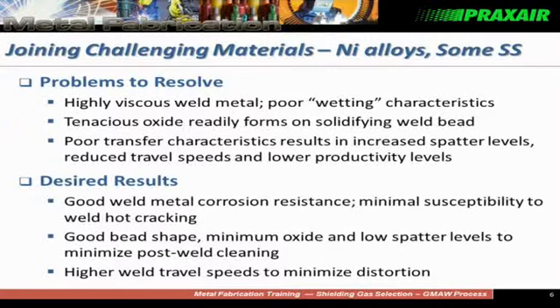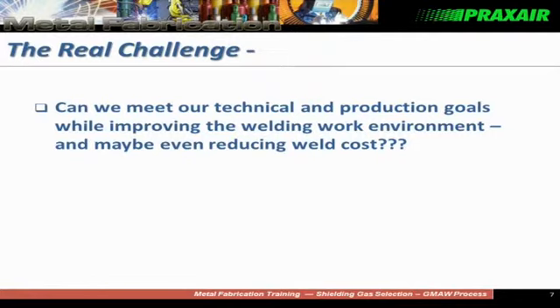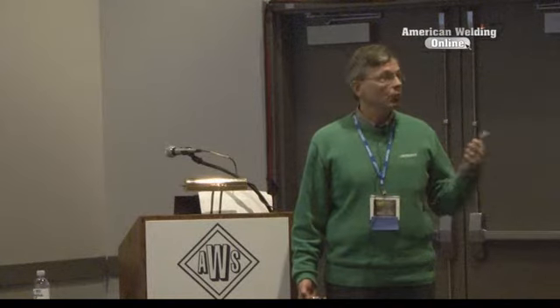So we looked at this area as to see what can we do with some of those variables I mentioned: shielding gas, power supply, parameter optimization, to make this welding process better, and how does that affect process optimization from a cost standpoint, and also from some of the other things that we talked about. So the desired result is obviously we want a good quality weld metal, and we'd like to minimize the amount of post-weld processing. So that's grinding, defect removal, anything like that. And obviously to be more productive if we could get travel speeds, in fact, higher. So the idea here is, can we meet the technical goals, the actual goal of fabricating a material out of these nickel alloys while improving the overall work environment, which means from a welding fume standpoint, from a noise standpoint, from a dust and dirt standpoint.